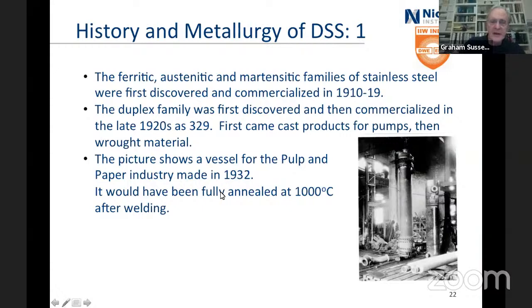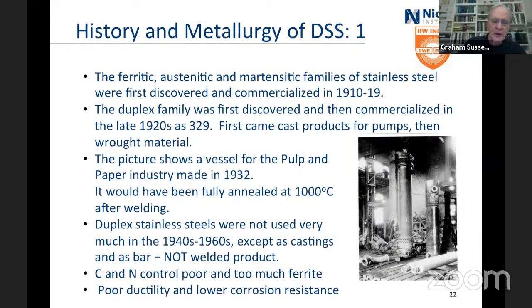1932. And they would have had to anneal at 1000 degrees C after welding because they weren't able to control the carbon and the nitrogen in that, and they actually weren't able to reliably put it in. So while they were used in the 40s to the 60s, it was as castings and bar, but not as welded product. Not good ductility and lower corrosion resistance because you couldn't get a decent balance between ferrite and austenite, and that's quite important.